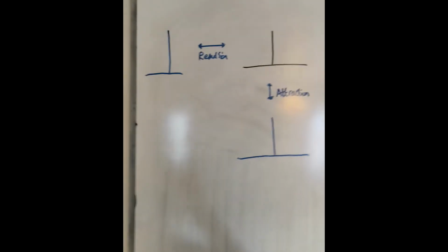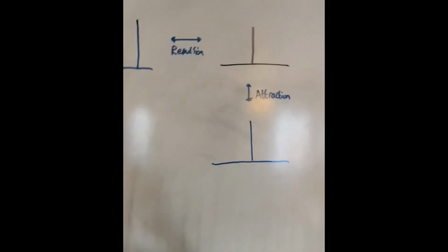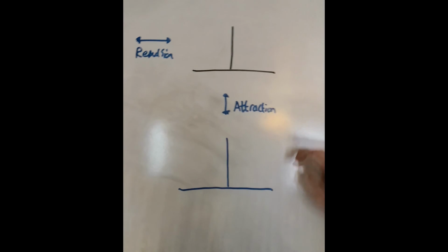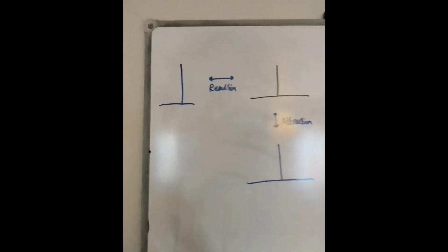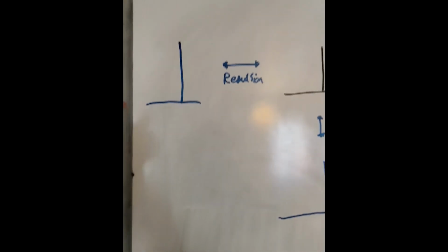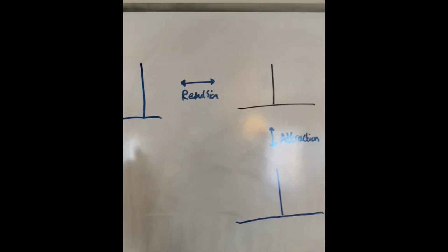And so what we can have in that scenario is two edge dislocations on separate glide planes which attract each other, and as they move through the structure they'll follow each other. If we have another edge dislocation on the same glide plane as this, there's repulsion, as explained earlier, between the two.